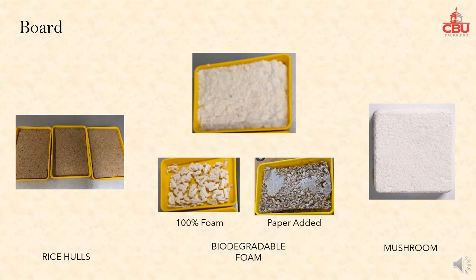The rice hull paperboard and biodegradable paperboard were made the same way as in several previous rice hull studies. A previous study showed that when 100% rice hulls were used, the board disintegrated. This also happened with biodegradable foam. Thus, paper was added into the wet pulps of biodegradable foam. Mushroom brick was purchased.